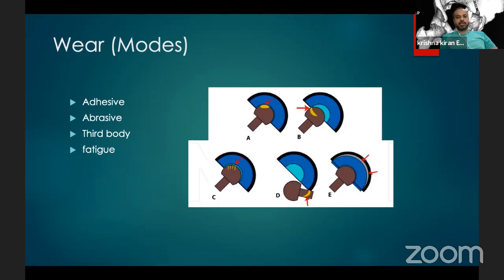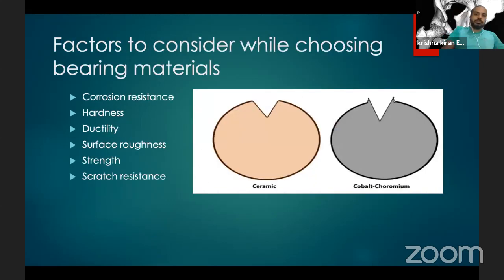The primary articulation is likely to be between the femoral head and the polyethylene liner or whatever insert we are using. But the secondary articulations, between the polyethylene liner and the cup, which is a backside wear, or in cases of impingement between the neck and the cup, which are not intended to be the primary modes of articulation, are the ones which give rise to the secondary wear.